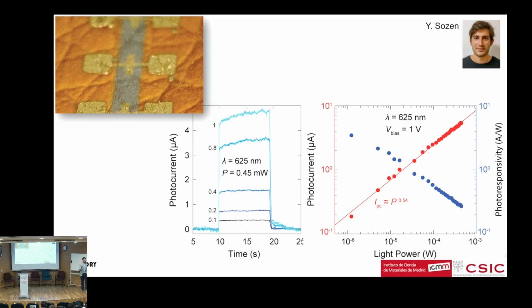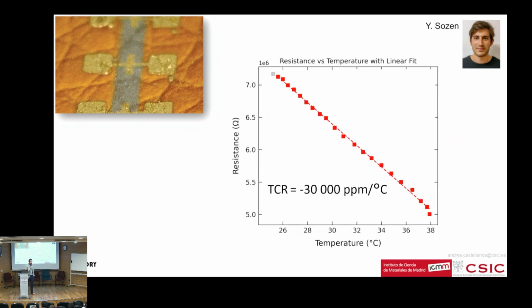Responsivity is one of the figures of merit of photodetectors. To have a comparison, a commercial silicon photodetector has a responsivity of 0.1 to, in the best case scenario, 1 ampere per watt. And these devices are already above 1 ampere per watt. Of course, there are other figures of merit in which these devices are worse, but I'm not going to show them.